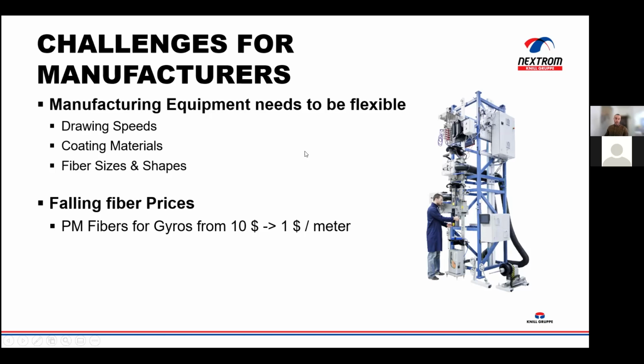The fiber sizes and shapes, as I talked about the different diameters, you have different needs for lengths, and specialty fibers may not even be truly a fiber. They can go up to millimeters in diameter, and at some point you refer to them as a cane or a rod rather than a fiber. And that again requires different equipment, because as the diameter of the fiber increases, the minimum bending radius is also increasing accordingly. And you're no longer able to bend it around a turn wheel, for example, or wind it onto a reel, and you need to cut it in straight lengths.